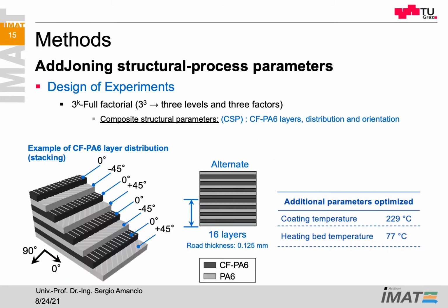orientation. And as an example here for the alternate, we have 16 layers where in this example we have 0 degrees in the carbon reinforced, plus minus 45 on the unreinforced, and so on and so forth. We use a coating temperature of 229 degrees and a heating bed temperature of 77 degrees Celsius.